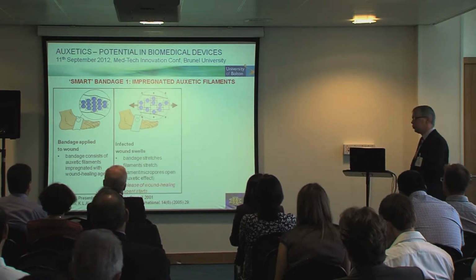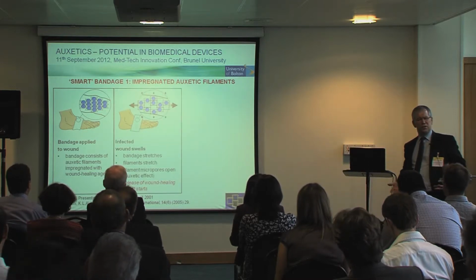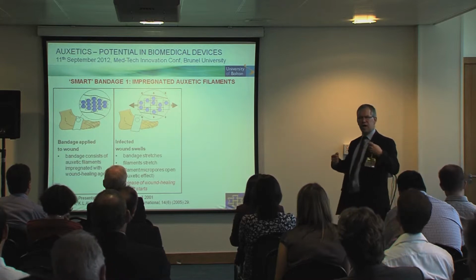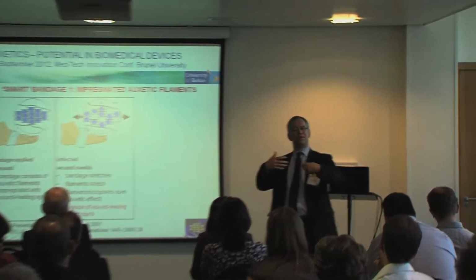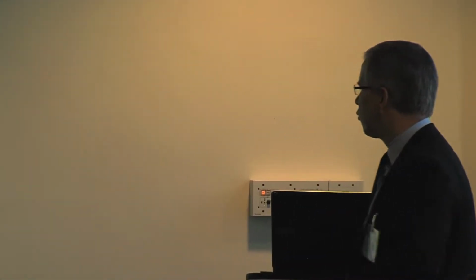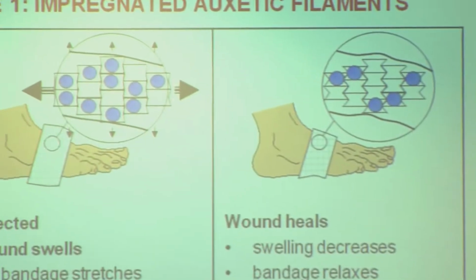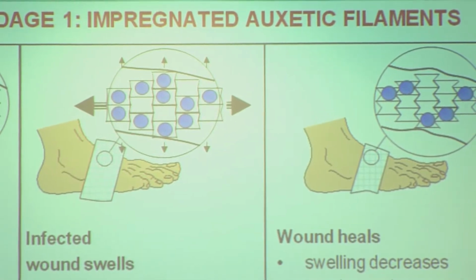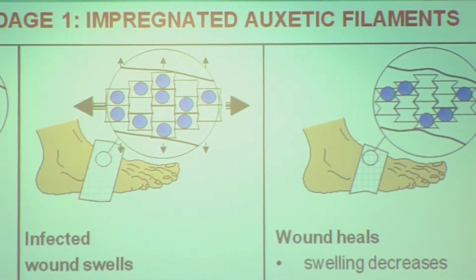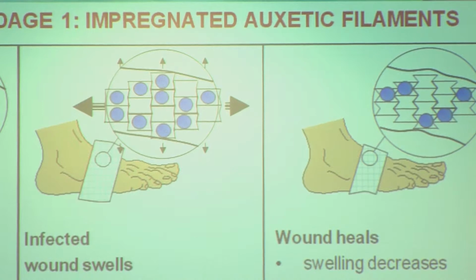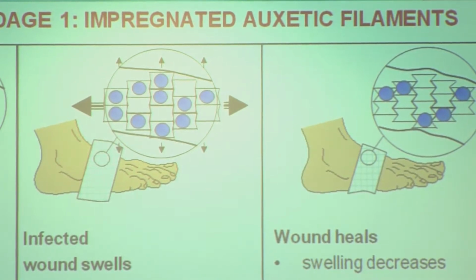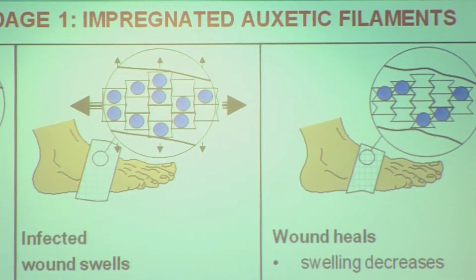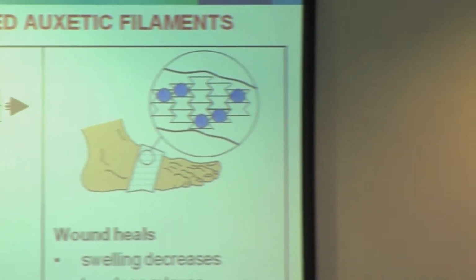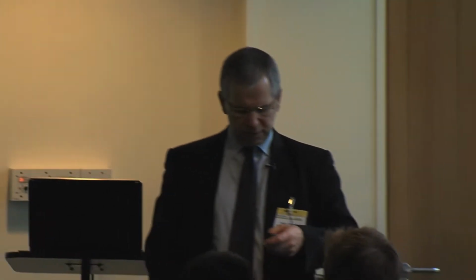And as the wound swells, what will that do? It stretches the bandage, it stretches the fibres, the fibre micropores open up, they release the active ingredient onto the wound, okay? Once the wound swelling goes down, the fibres relax back, the pores close up, and you switch off the release of the drug. Okay? Any secondary inflammation would reactivate that bandage to restart the drug release. So we believe that's a genuinely smart concept, and a number of these components of that concept we've proved now.